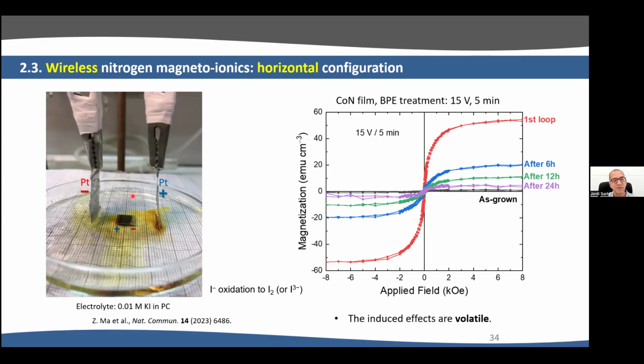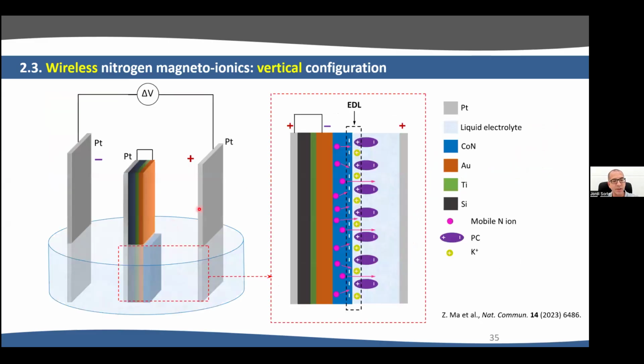But the problem of this configuration is that after some hours, the ferromagnetic response starts to decrease. It decreases because there is a diffusion back of nitrogen laterally, and this cobalt tends to get nitrided again. So in order to minimize this, we changed the configuration from horizontal to vertical. Now in this configuration, the whole film is exposed to this bipolar electrochemistry, so we release nitrogen from the whole film. And we thought that because now the distance between the negative and the positive is very narrow, maybe the effect is non-volatile. And actually, this is what happened.